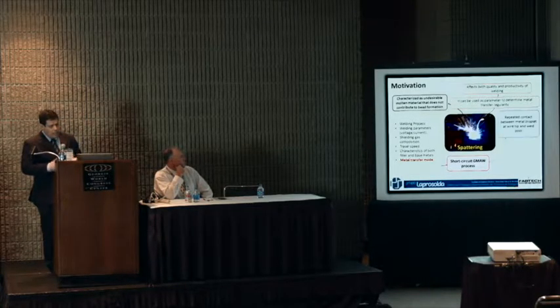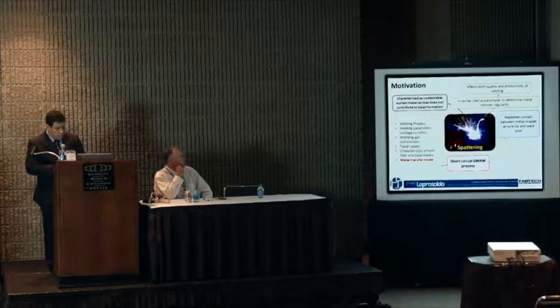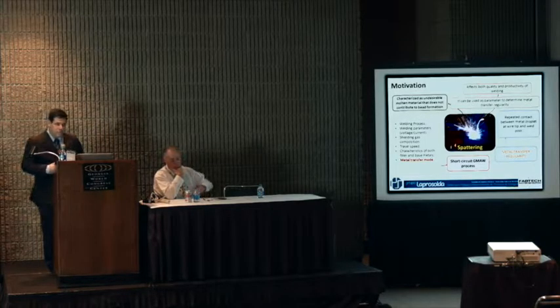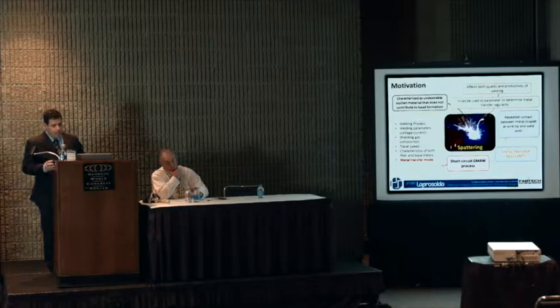Spatter comes from the short circuit, from the periodic contact between the metal drop, the wire and the weld pool. Let's try to establish a relationship between the regularity of the metal transfer and spatter reduction. I would like to point out that we are not saying stability of the metal transfer, we are saying regularity, because stability is a little more complex, which is stable, which is unstable. Here we talk about regularity, which means that independently of the time, we have the same frequency, the same open arc time, the same short circuit time. We talk about constancy here, not stability.